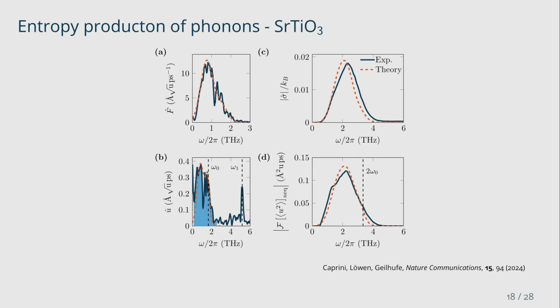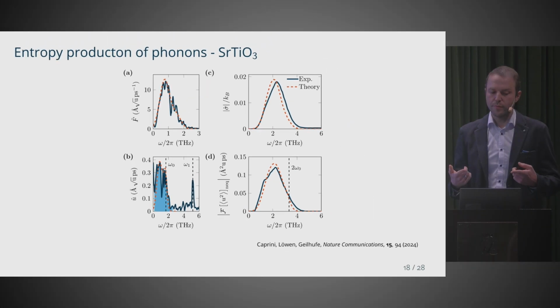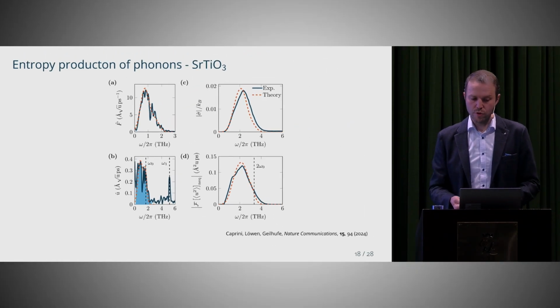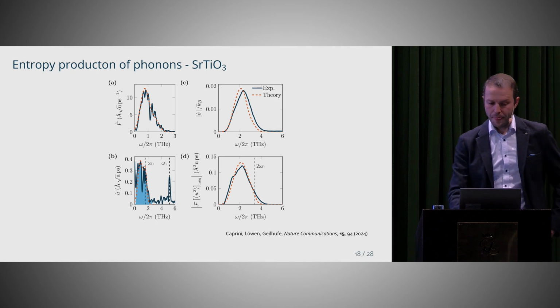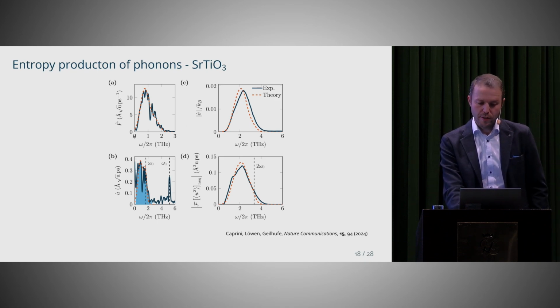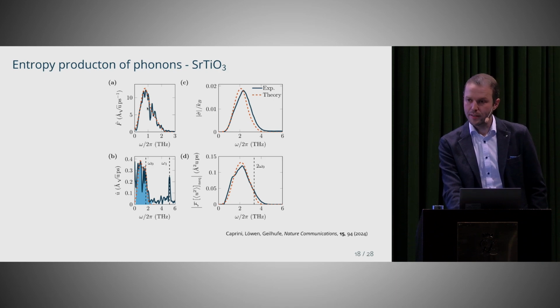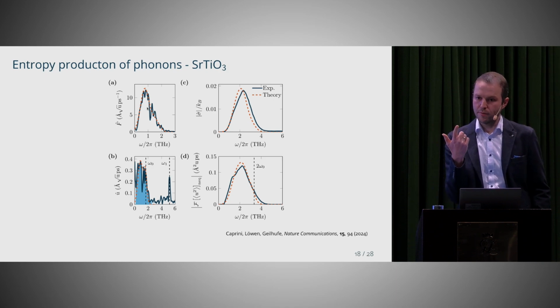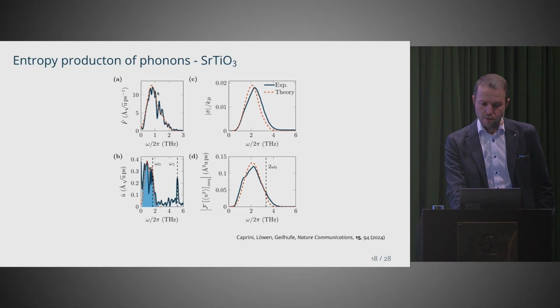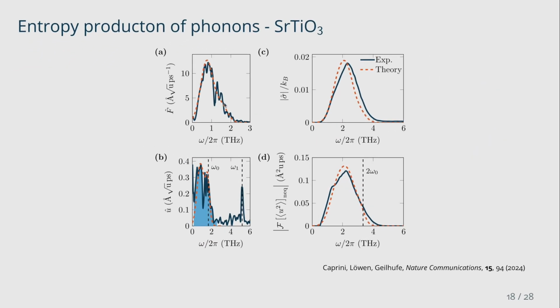And then we developed our theory. We were aware of this experiment, so we could reuse some of the data that was produced. I'm now showing a couple of plots. Plot A is the laser pulse. The blue curve is the experimental laser pulse. Remember, there were two quantities that we want to know, the laser pulse and the velocity. The laser pulse is pretty much known trivially, so that is what experimentalists use before they even start to study the material.